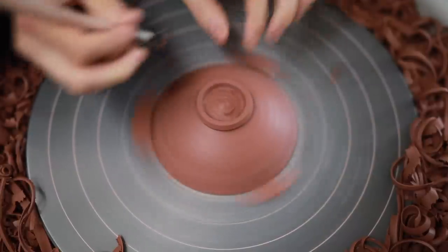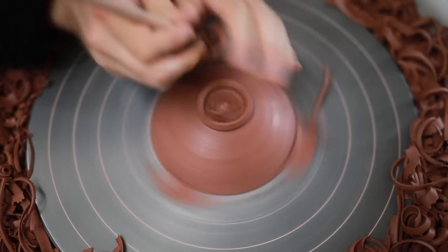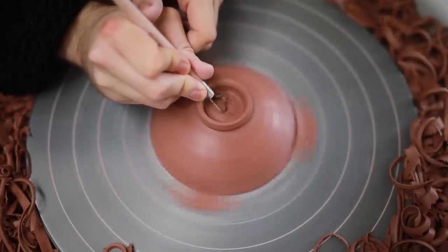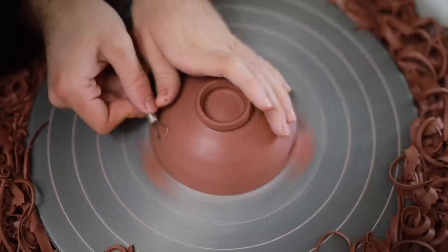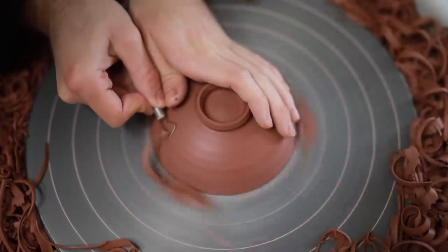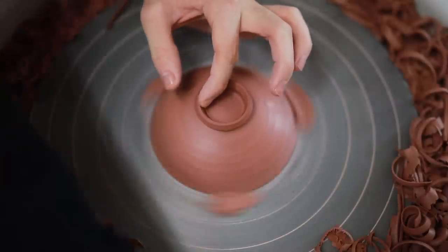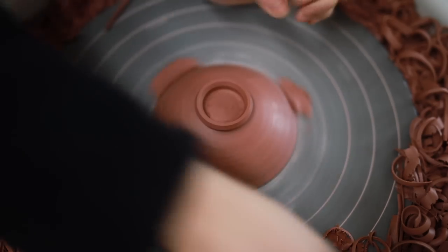There are two moments where you need to be more careful — these bowls are a good example of that with their delicate small feet. But leading up to that, the lower half of the walls and the supporting clay should be removed quickly and with real conviction. That's why it's so important to make sure that the clay's condition is at the right kind of dryness before you start to trim it. If it's too soft, the bowl will deform as you push down with the trimming tool, and the ribbons of clay that come off will stick back to the bowl, so you'll constantly have to be stopping the wheel to remove them. Equally, if the bowl is too firm, you'll have just as much trouble trimming it, and you can even hurt your wrist. Instead of ribbons coming off in lovely long strands, they'll come off in tiny shards and your overall progress will be far slower. It isn't always the easiest to keep constant watch over your clay — sometimes overnight pots will dry out more than you think, and you have to work with whatever condition the clay is in anyway. But I'm sure as any potter knows, it really feels good when the clay is in just the right condition.